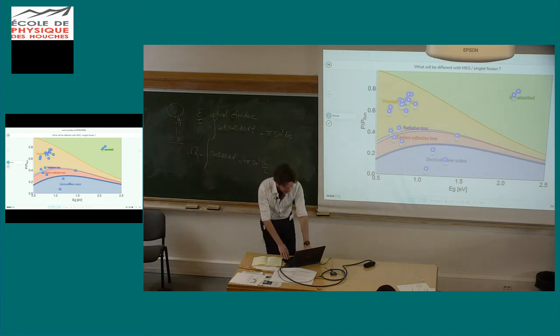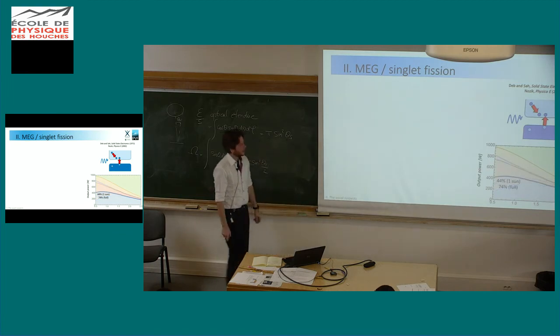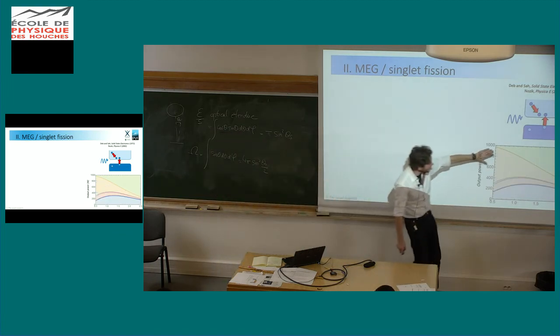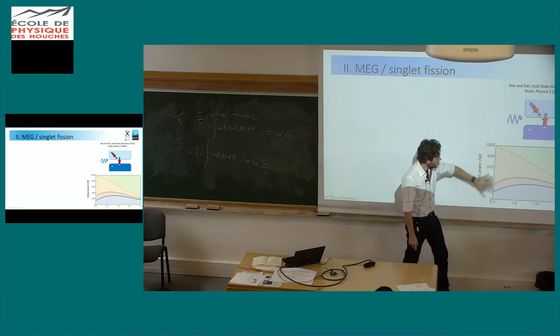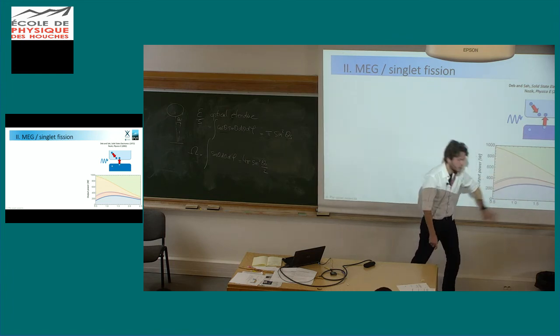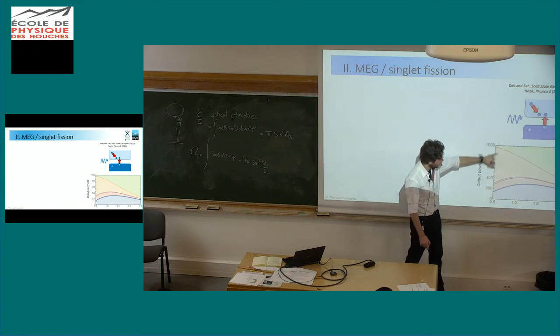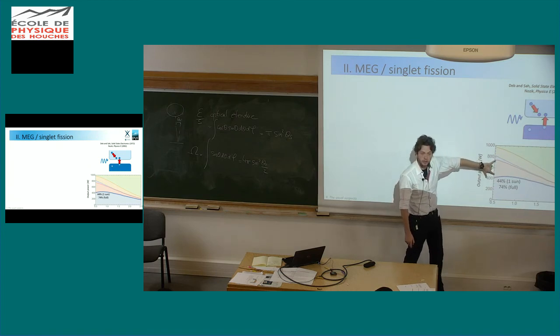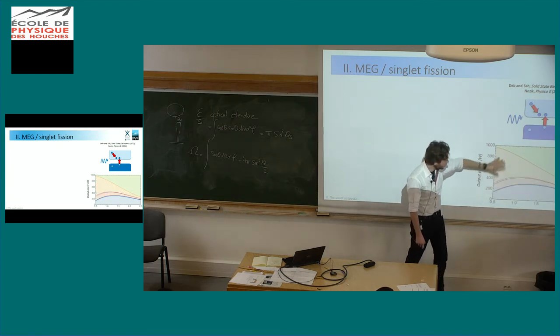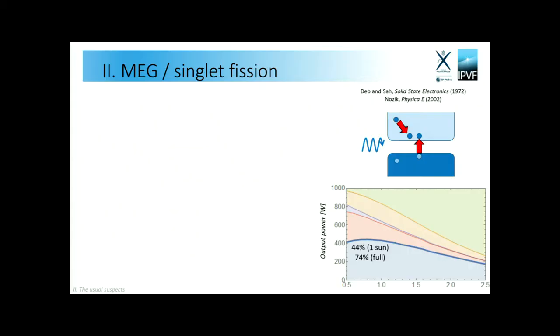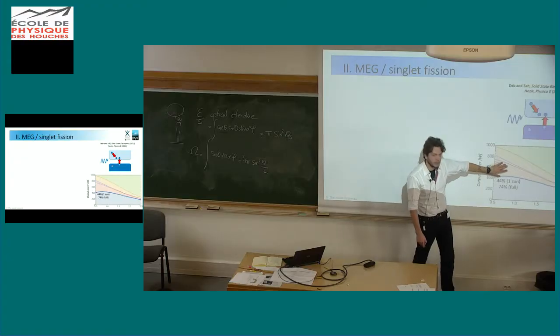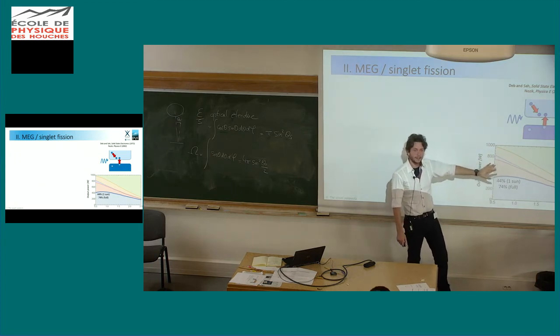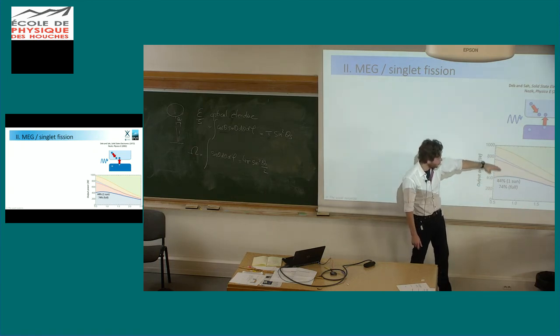So what is really happening is quite similar to what happened before, this idea that instead of wasting energy due to thermalization here, we're using this energy to make carriers which we're going to use for electricity. So we're reducing thermalization losses. Now what is quite interesting here is to see that this red contribution is super high, which means if you do this at low gap, you're going to have significant collection losses, which also means that this should really be made specifically under concentration, because concentration will help you take advantage of these losses.